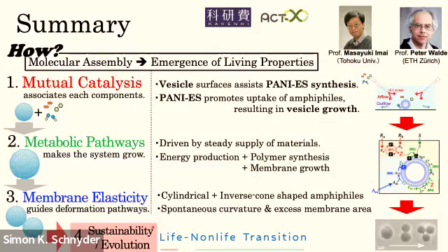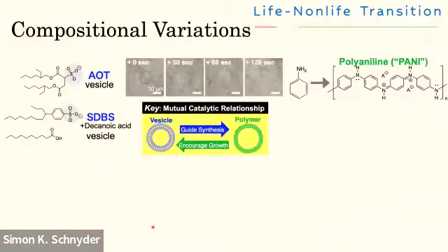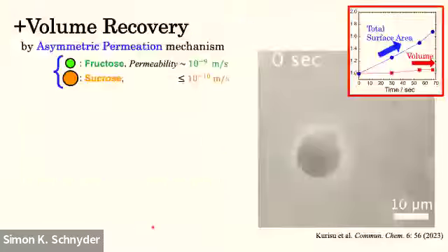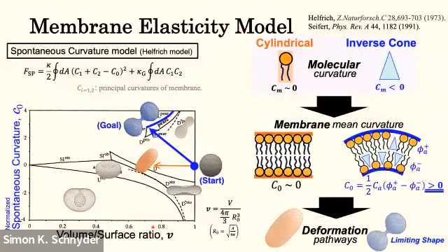You mentioned adding inverted cone lipids in order to make a positive spontaneous curvature, because of the redistribution across the leaflets, but the flipping of the lipids across the leaflets is actually very slow. So you might want to consider already making an asymmetric membrane, because otherwise I cannot see how it works. The redistribution will be very slow, I think.